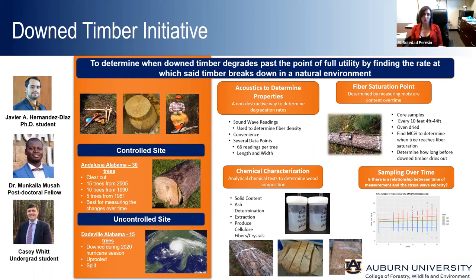usable end product. So far, our preliminary data indicates that at least the cellulose component of these materials takes about 36 weeks to degrade, which is wonderful news for applications like ours in terms of the utilization of cellulose for nanocellulose and added products.